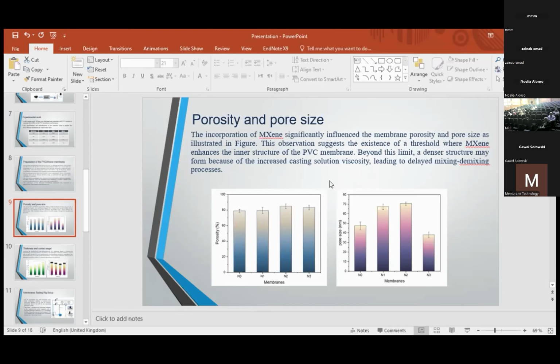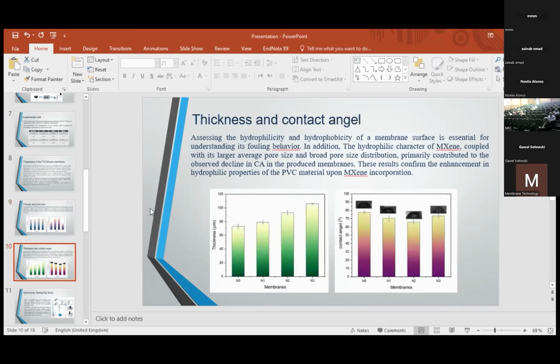Beyond this limit, a denser structure may form because of the increased casting solution viscosity, leading to a delayed demixing process. In addition, the hydrophilic character of MXene, coupled with its larger average pore size and broad pore size distribution, primarily contributed to the observed decline in contact angle in the produced membrane. These results confirm the enhancement in hydrophilic properties of the PVC material upon MXene incorporation.